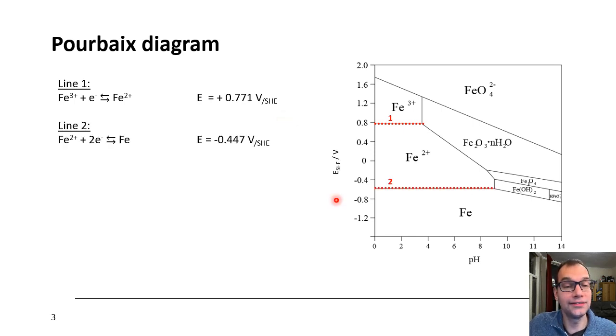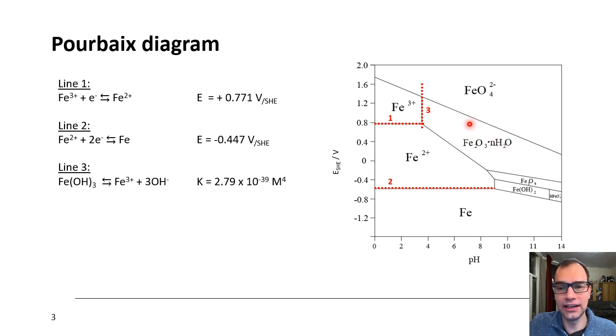Another relatively easy to understand line is the line between iron 2 and metallic iron, which you see here. And that corresponds to this equation with this potential. Now, there are also these vertical lines, such as line 3. Line 3 is, as you can see, on one hand we have iron 3, and on the other side we have iron 2O3. If you just think about the oxidation states, then you see that the iron in this molecule is still iron 3. So this is not a redox reaction. Actually, it's just a solubility product, and that's what you can see here.